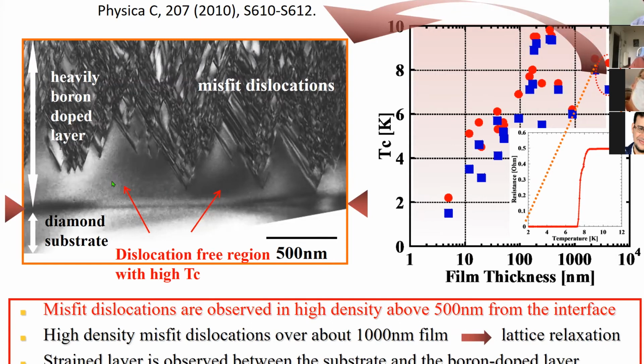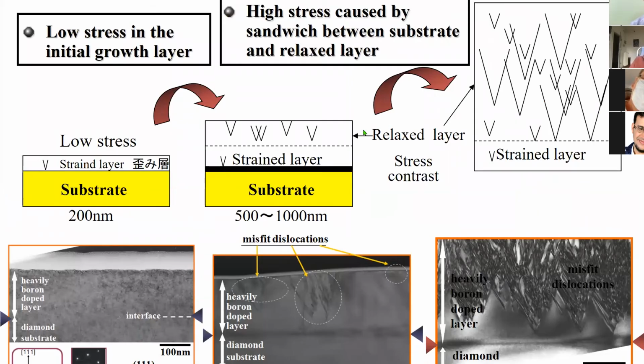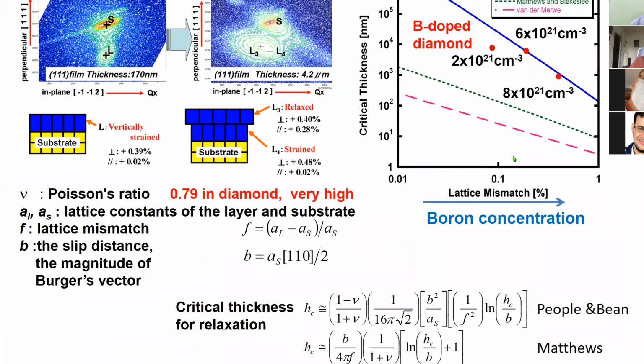So the difference between this defective region and the non-defective region is that in the defective region the stress is not yet relaxed. This is a schematic view to summarize what's happening. The strain layers we have here are very influential for the high TC in our case. We changed the boron concentrations and looked at the critical thickness concept, critical thickness being where the strain layer becomes relaxed.